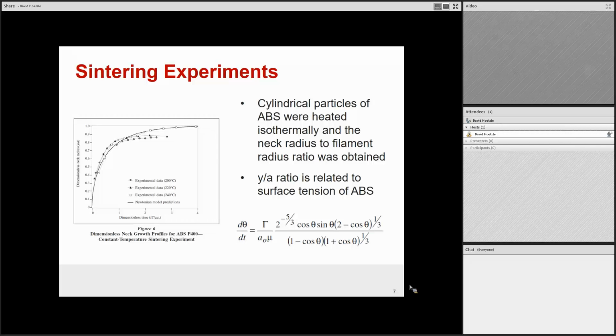So the goal of these sintering experiments was to figure out the relationship between surface tension and the actual thermal conditions that you're creating. So what they did is, as they heated these, they measured the net growth as a ratio of the radius of each of the filaments. And they're able to use the function in the lower right-hand corner to model the surface tension with respect to time. The gamma is the surface tension in units, I believe, newtons per meter. And then the theta is a trigonometric expression of the ratio of the net growth versus the radius of the filament.